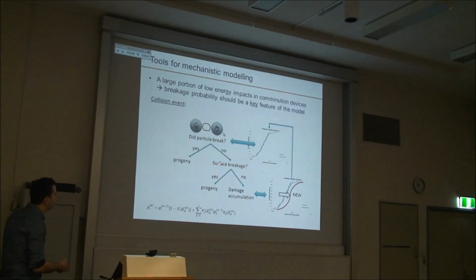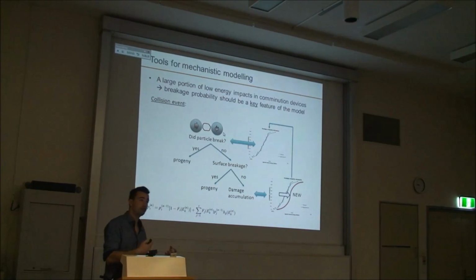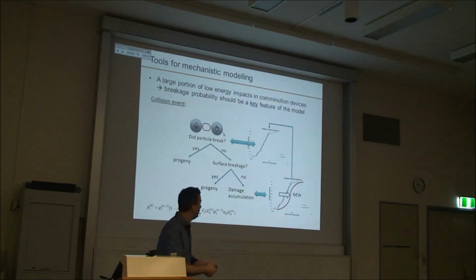So then, if the particle didn't break, does the particle have surface breakage? Yes or no. You have different progeny and appearance function in the case of surface breakage. And if it didn't break and it didn't have surface damage or abrasion, does it have damage accumulation? This is quite important as well, because during those low energy collisions, you will have damage accumulation.